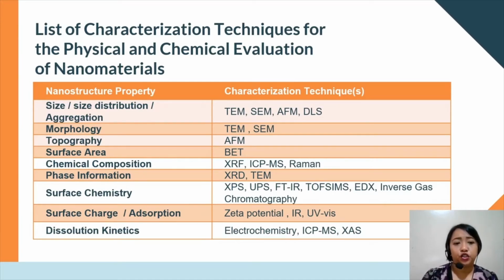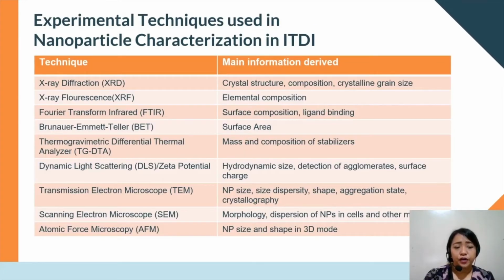Surface charge and adsorption property, we can use the dynamic light scattering with the capability of zeta potential measurement, IR, and UV-vis. And for the dissolution kinetics, we can use electrochemistry, ICP-MS, and XAS. So here are the experimental techniques used in nanoparticle characterization in ITDI.